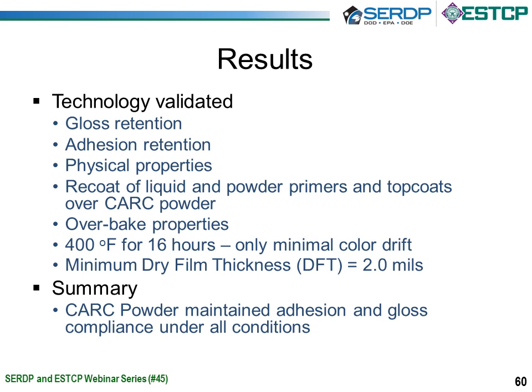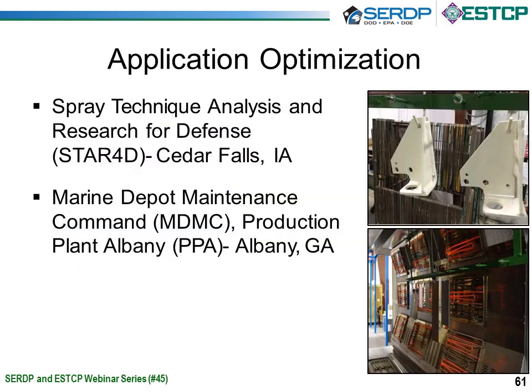And finally, that's the result of how we arrived at our recommendation of 2 mils of film thickness. So the result of this, basically to summarize, is we have developed a CARC powder that maintains all the physical, appearance and application properties that are defined, and the conditions under which it can be applied. So that's the first stage of commercialization.